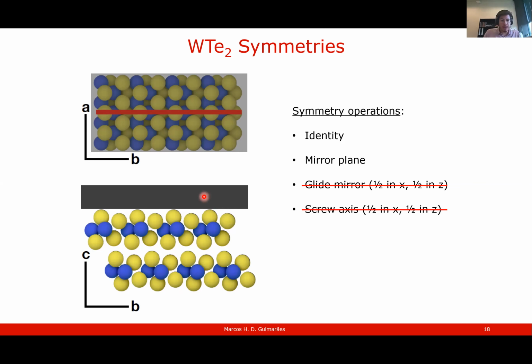Yes, that's true. The spin-orbit torques will be affected quite a lot by the spin transparency through the interface. For example, for the spin Hall effect, one naive way to think about it is that if you create spins in the tungsten ditelluride, you need to transmit them into the ferromagnet, and if this interface is very bad, then the spins cannot go through. Okay. So it is very difficult to make these types of devices, as I think you know. Sometimes we do get poor interface qualities.